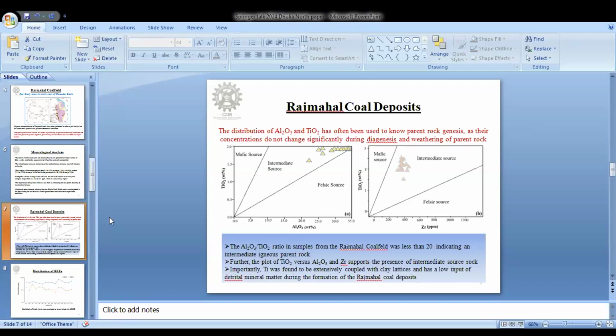Furthermore, the plot of TiO2 versus aluminum oxide and zircon supports the presence of intermediate source rock. And titanium was found to be extensively coupled with clay lattices, which was supported by XRD analysis as well, which I haven't shown in the presentation. But titanium primarily exists as anatase or rutile. So we found that it was extensively coupled with clay lattices and has a low input of detrital mineral matter during the formation of the coal deposits of this particular area.